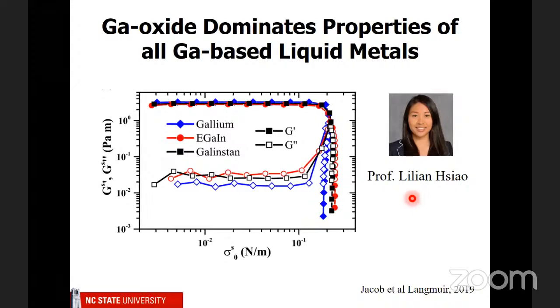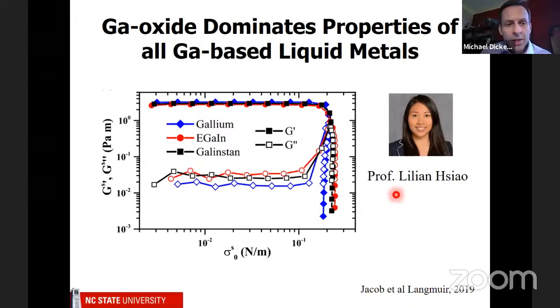We actually went in with my colleague, Professor Hsiao, and her student, and we looked at gallium. So this is just pure gallium, gallium indium, and then this is called Galinstan, which is gallium indium tin. And you'll see that all of them are exactly the same. What that means is that even though you change the composition of the liquid metal by adding indium, for example, it's really gallium oxide that dominates the properties. So everything I'm going to show you would work for gallium, gallium indium tin. It doesn't matter. As long as it has gallium, it's going to be gallium oxide.